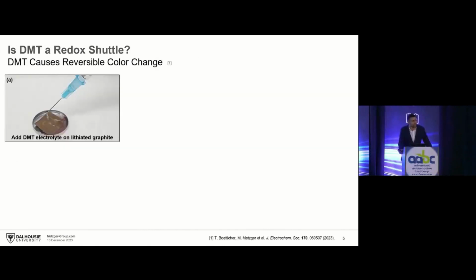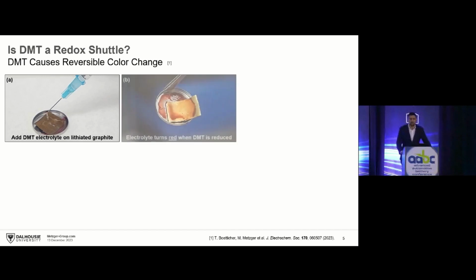But we did a simple test to show that DMT is truly a redox shuttle. We have our pristine electrolyte to which we add the DMT molecule. If we do that, the electrolyte is clear, and we can pipette it on top of a lithiated graphite electrode. Here you see this nice golden piece of graphite. So it's a negative electrode which is at a low voltage. And if we put that electrolyte on this piece of electrode, after a few seconds it turns red, which is really in good agreement with the color change we have been seeing in our battery electrolyte.